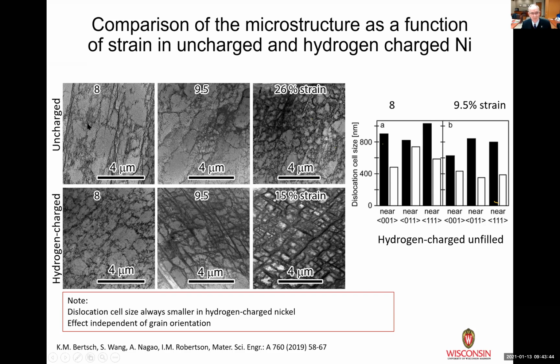So you'll see a comparison at 8% strain, comparison at 9.5. In this case, the hydrogen charged one failed at 15%, and the other one didn't fail. It was still up at 26% strain. And if you look at the microstructures that I've been trying to get you to look at, 8% strain, no hydrogen, a sort of ill-defined cell structure. If I look at 8% with hydrogen, still the early stages of cell formation, but more formed than the uncharged. Right? Again, it goes to this accelerating effect.